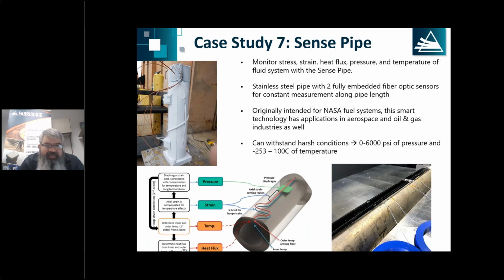One example of that is what we call the sense pipe. This was some work for NASA. They were interested in looking at both pressure and temperature fluctuations in a cryogenic fuel pipe while fuel is flowing to the rocket. So here we embedded some fiber optic sensors so that we could measure both strain and temperature along the length of the pipe and get some fairly high resolution data. As the rocket is consuming fuel, we're measuring the changes in pressure and temperature as that cryogenic fuel is flowing through the pipe leading up to the rocket.